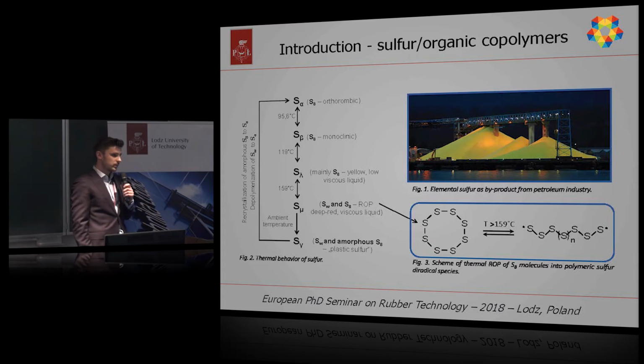The most thermodynamically stable form of sulfur is orthorhombic sulfur. During heating, it converts firstly to monoclinic sulfur, and then at temperature of approximately 119 Celsius degree, the crystals of monoclinic sulfur and orthorhombic sulfur melt into yellow low viscous liquid, and further heating leads to ring opening polymerization and resulting in creation of polymeric sulfur diradical species, which polymerize together into polymeric sulfur, described as Sμ.